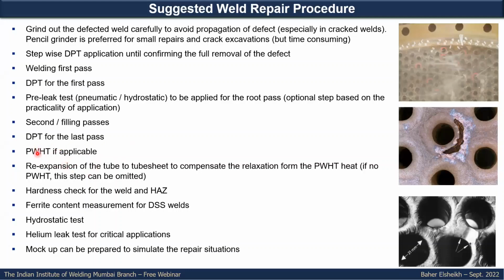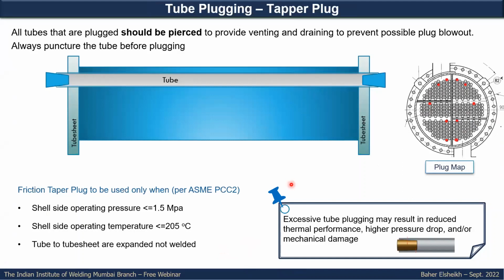And if you apply this one, you need to do the expanding again, do the hardness test, ferrite content if applicable, and the final hydro test and helium leak test if critical service requires helium leak test. During the preparation you might do the mock-up, especially for critical equipment, before trying to do any repair.